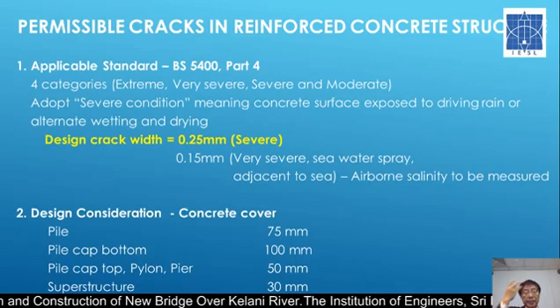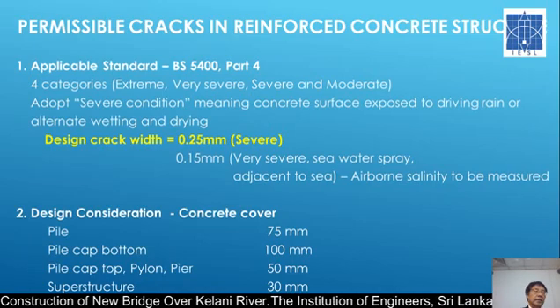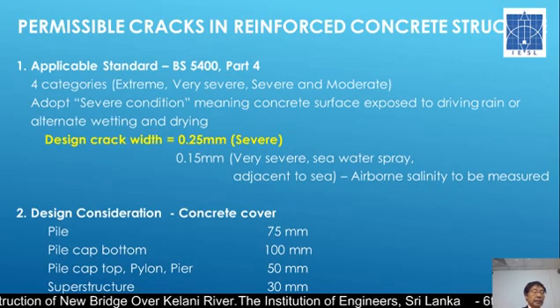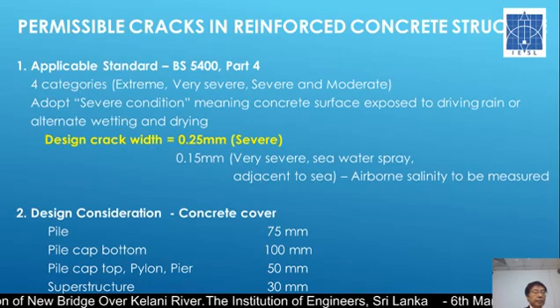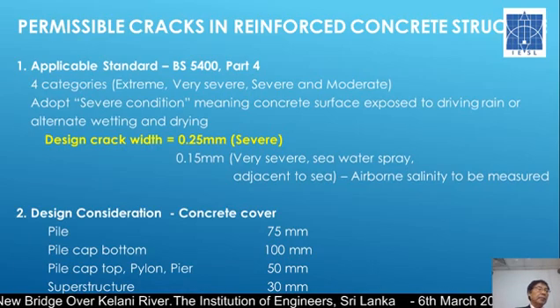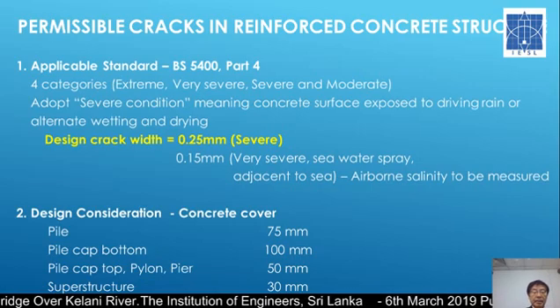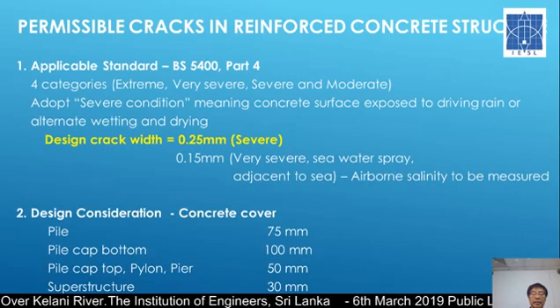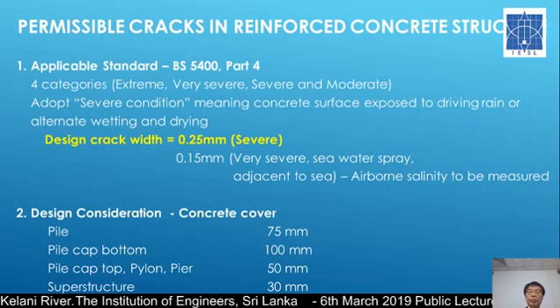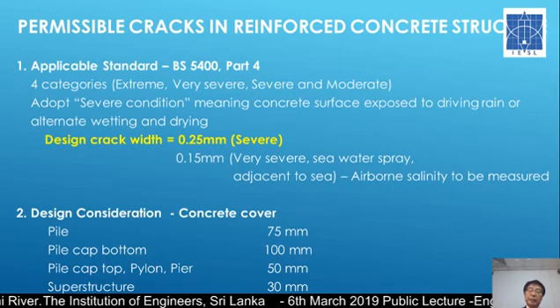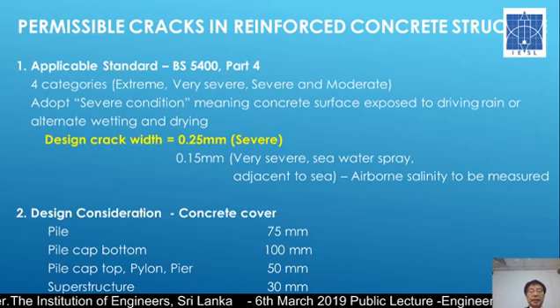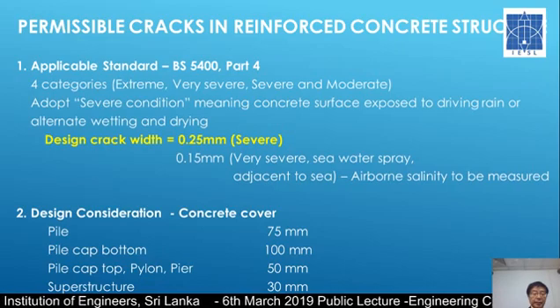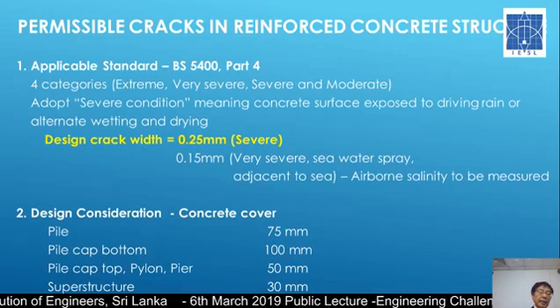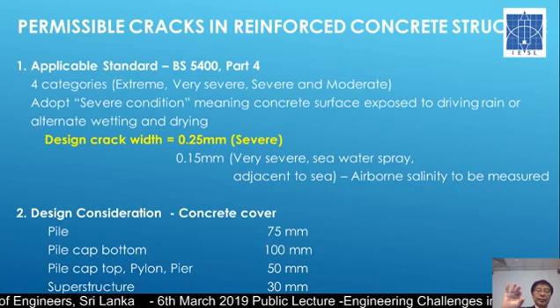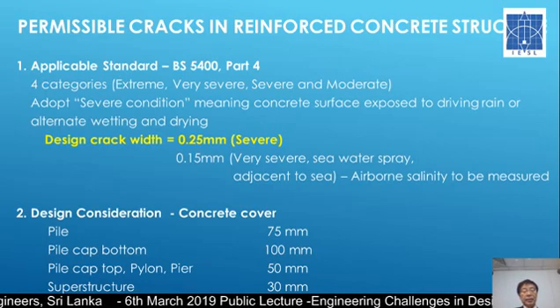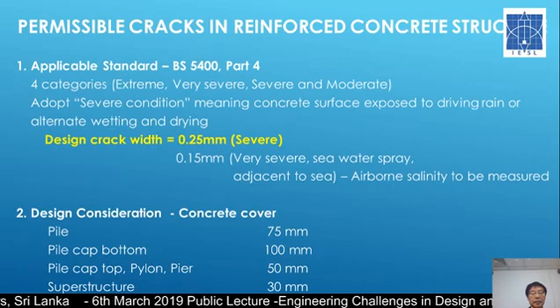Now, I'm confusing you a little bit, but according to the permissible cracking in reinforced concrete, as I already mentioned, the allowable crack width is determined by the British Standard, and for the severe environmental condition, it is defined as 0.25. But for very severe, like seawater spray, which is only applicable to structures built adjacent to the sea, it is 0.15. Of course, it is more susceptible to airborne chlorine, so the crack width is to be reduced. But in addition, in the design we have a sufficient depth of cover. Cover means the depth between the rebar and the concrete surface, which is determined like this, much higher than normal structural design.